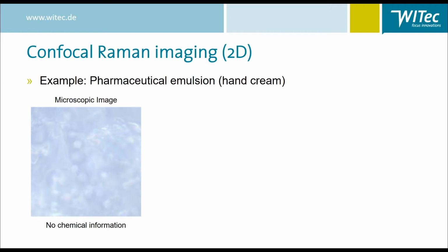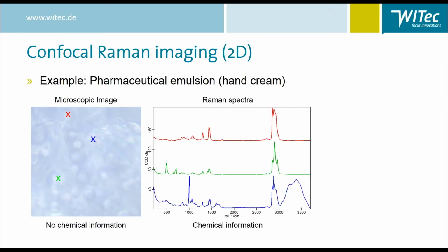Of course, we can measure the Raman spectrum at specific positions to identify the components. At the blue position, we find an aqueous phase with a very broad peak at the right end of the spectrum, which indicates water. The red spectrum, measured on one of these bubble-like shapes, is an organic phase. And the green spectrum, measured on another bubble, reveals Raman peaks that are characteristic for urea. And now we can apply Raman imaging to get the full picture.